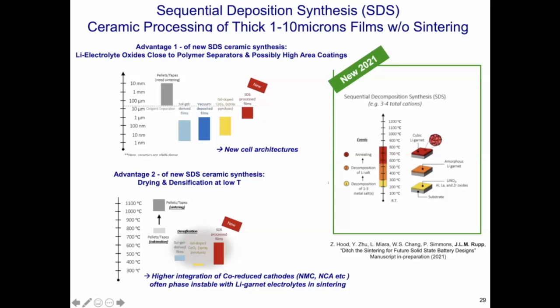Why is that relevant? Well, if we can process now at 600, 650, you can bring in LFP or other structures like NMC or NCA as cathodes that are normally not stable in classic sintering, when you have to go to very high temperatures.